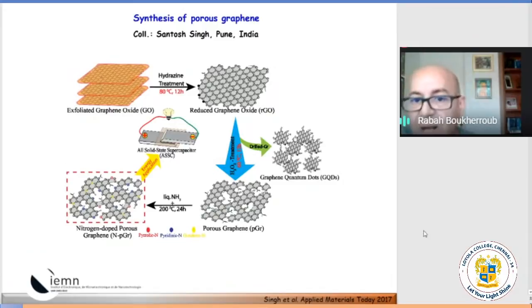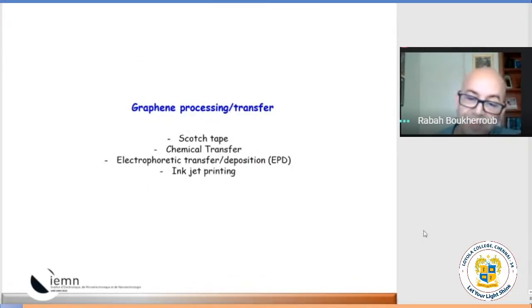And if you're not happy enough, of course, there's a lot more you can do. This was actually a collaboration we had with a young PhD student who came from India for 6 months in the lab. It's to go a little bit further to improve the properties of the graphene or reduced graphene oxide through doping, or making porous material out of the graphene so you can increase the surface area. Or you can even make what you call graphene quantum dots. These are just very small structures made out of graphene.